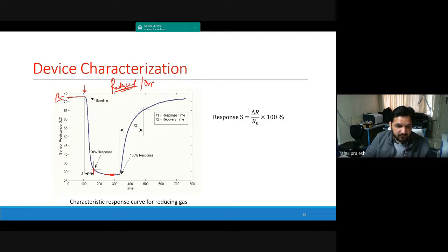So from this time T1 to this point is called the response time. And from when you switch off the gas and only air is flowing, the recovery starts, and this is the saturation. This is 90% of the saturation. This is your recovery time. And you can calculate the change in resistance from this point to this point. So delta R is calculated and divided by the initial resistance. That gives you the response. So you can calculate response, response time, and recovery time from the same curve, and you have 3 parameters. That's how you characterize your device.